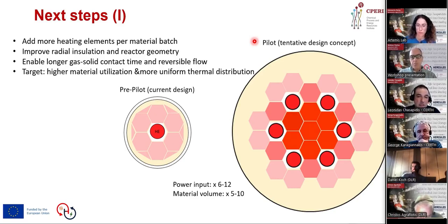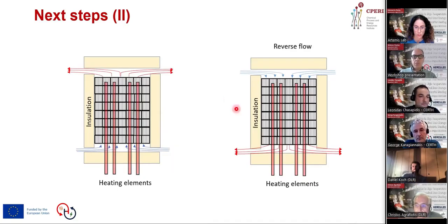Specifically, the pilot design will include more heating elements per volume of storage material, likely 6 instead of 1, to distribute the heat more evenly across the reactor. We also plan to improve the radial insulation, which should significantly reduce the heat losses and help stabilize the temperature profile. Next slide, please.